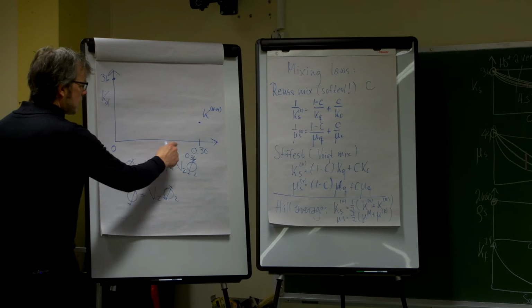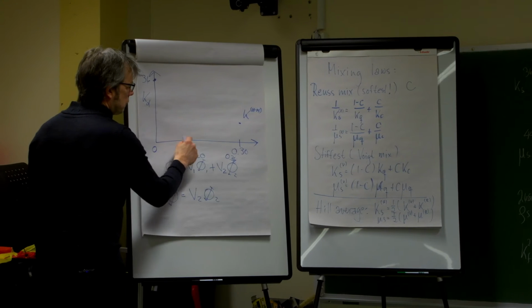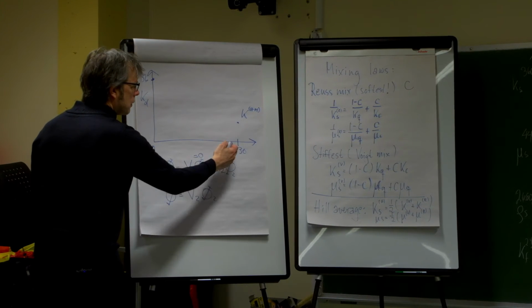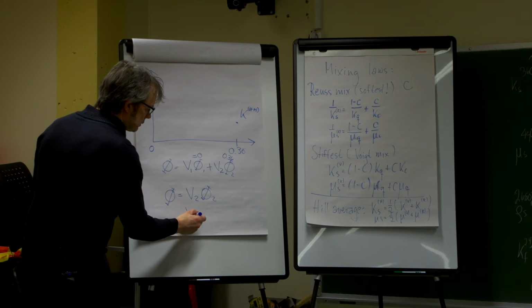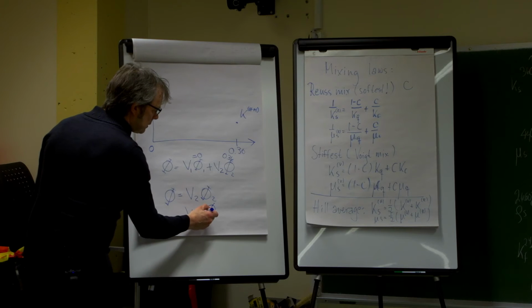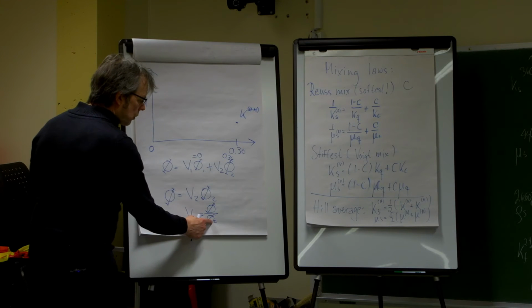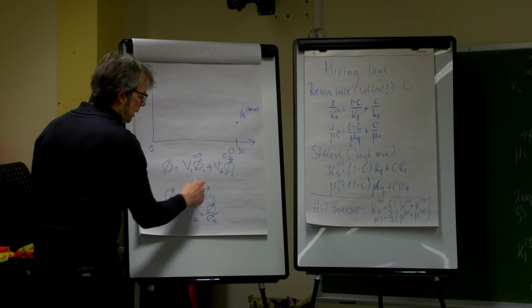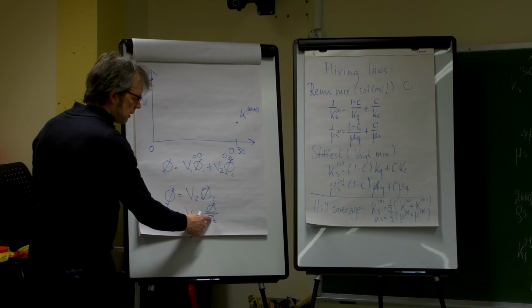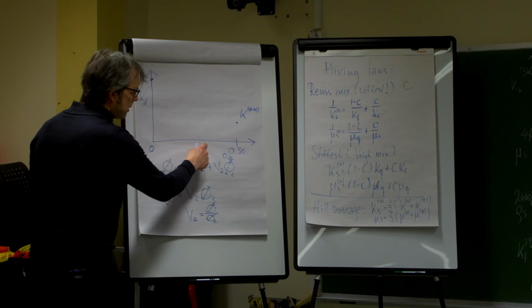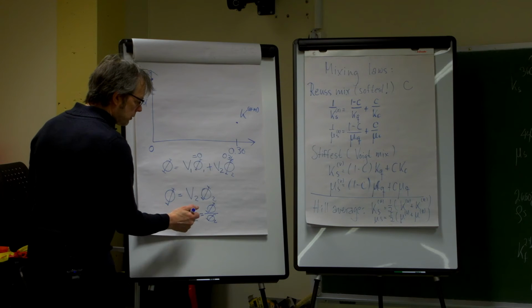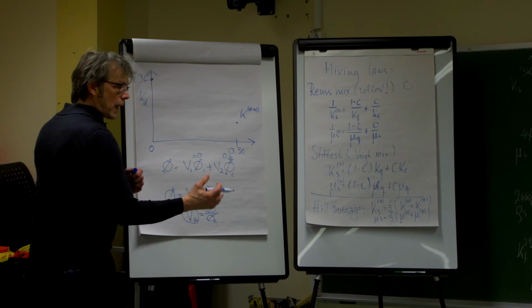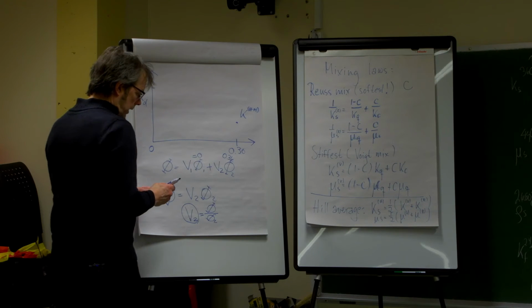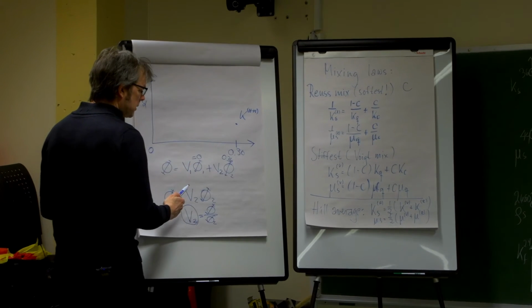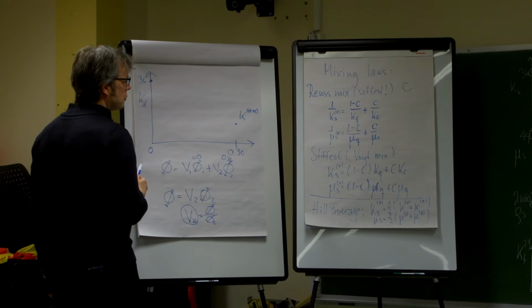So then we know for any porosity we want to interpolate, we can find how much of V2 we need. What this says is that V2 is simply the porosity divided by phi 2. So when I know the porosity at this point, and I want to do some averaging, giving me the value at any porosity in between the two end members, I can find how much of V2 I need to add in my mix here. Okay, so it's easy to find how much you need to mix of the two end members in order to arrive at a certain porosity.